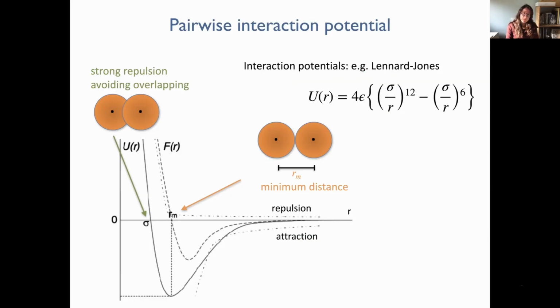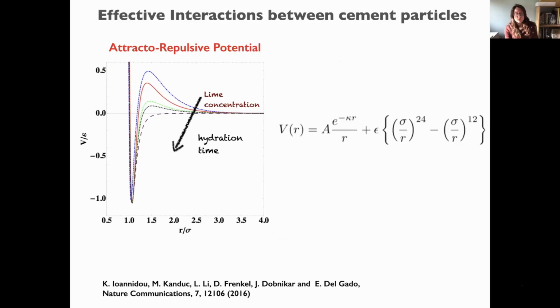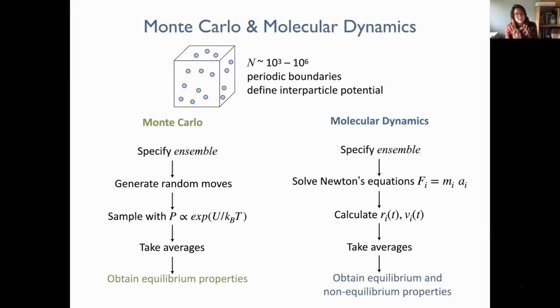To introduce this repulsive shoulder, we couple this potential with the Yukawa term. And to get the very strong attraction that exists in cement, we tweaked the exponents of the Lennard-Jones potential: instead of the usual 6-12, we used 12-24. This makes the interaction well more narrow and more sticky.